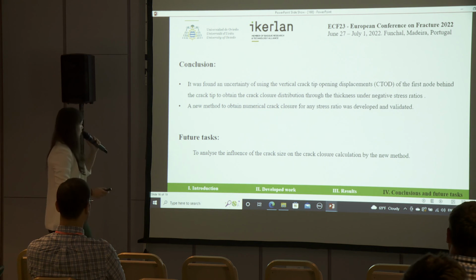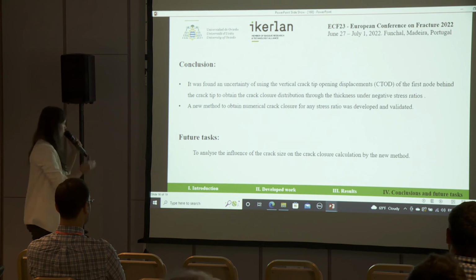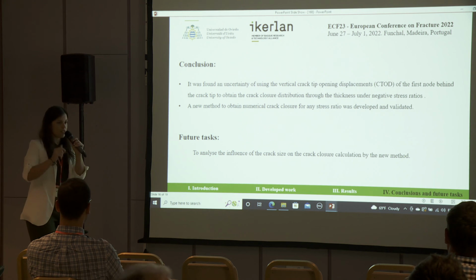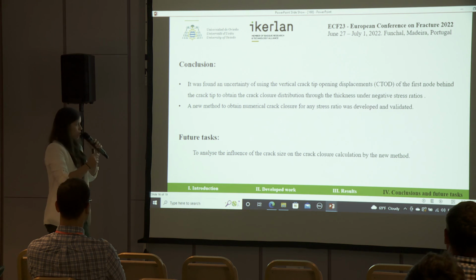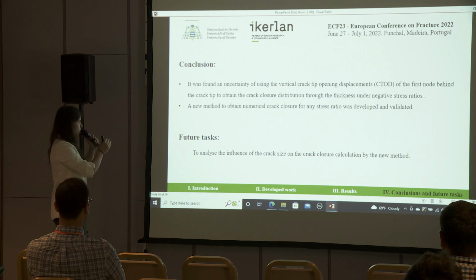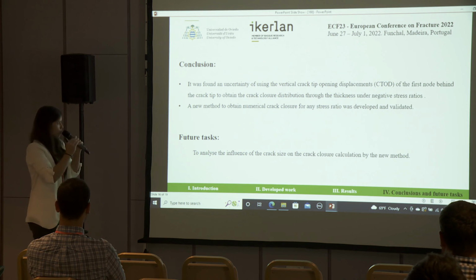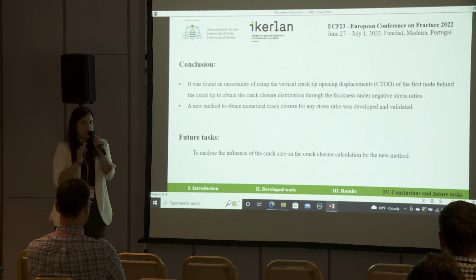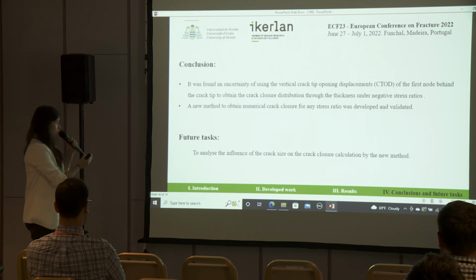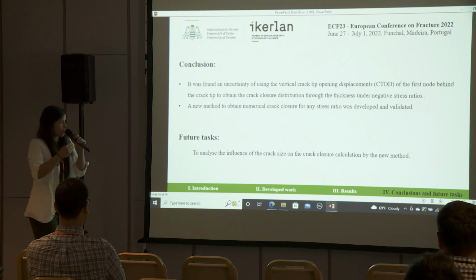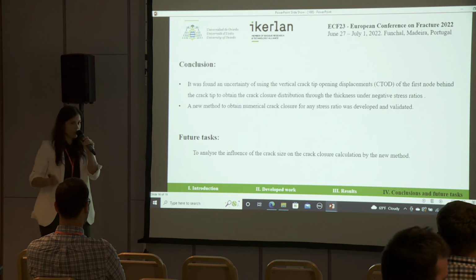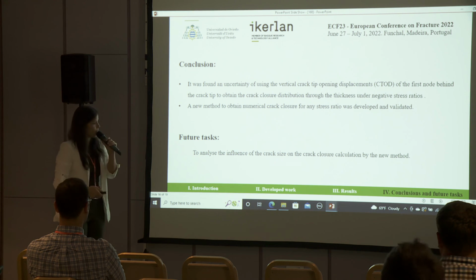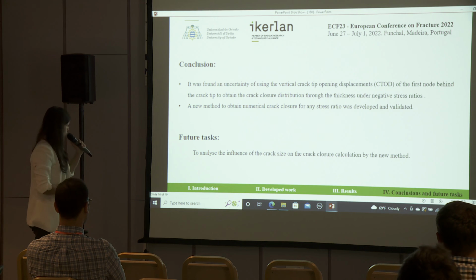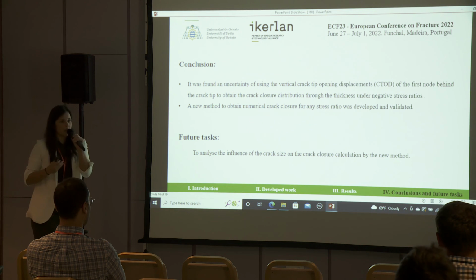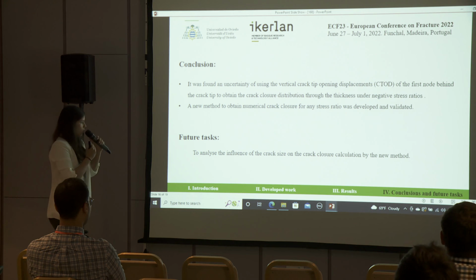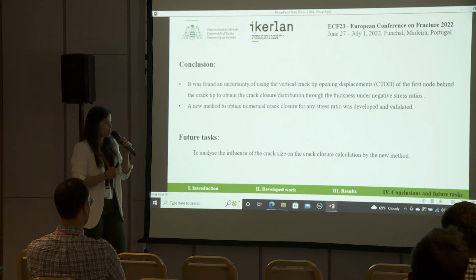So, summing up the main conclusion of this work, an uncertainty was found in using the vertical displacement of the first node behind the crack tip to obtain the crack closure distribution through a thickness under negative stress ratios. So, to solve this problem, a new method to obtain this numerical crack closure for any stress ratio was developed and validated. And to end the presentation, in future tasks, we will analyze the influence of the crack size on the crack closure calculation by the new method.